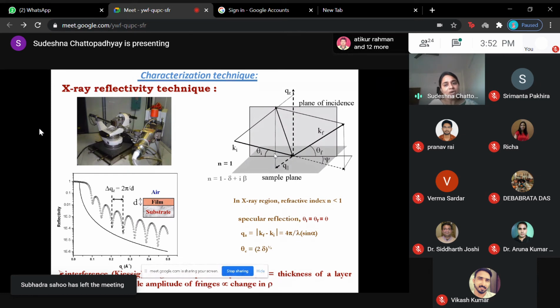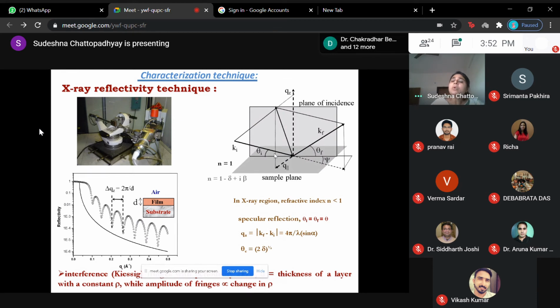For X-ray, the photons are coming from the lighter medium to the denser medium, that means from air to the material. If the angle is completely below the critical angle, the beam is completely externally reflected. So it is called total external reflection. If we go a little bit more than the critical angle, then it will start penetrating into the system. As I have shown here, this flat region is the reflectivity.